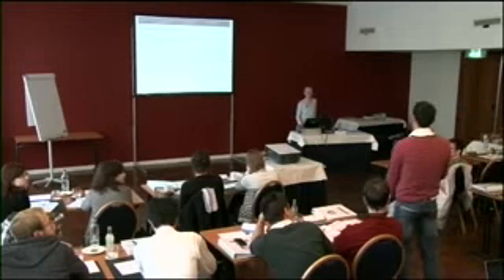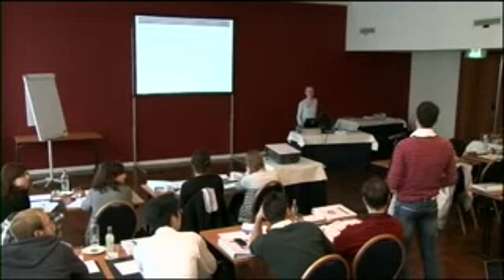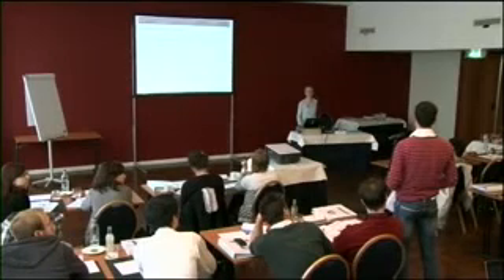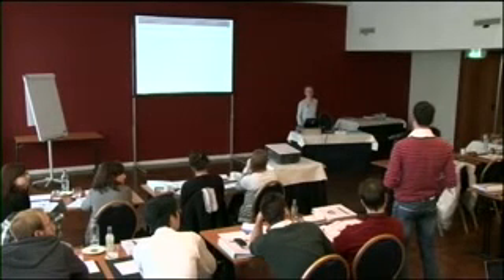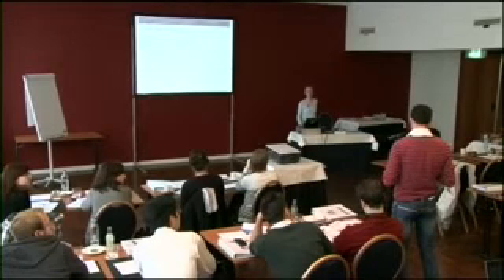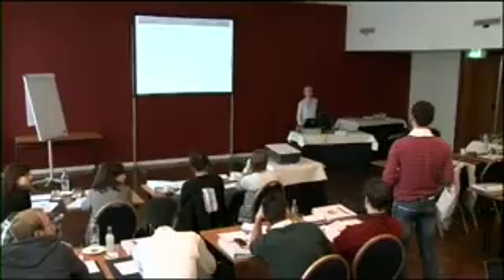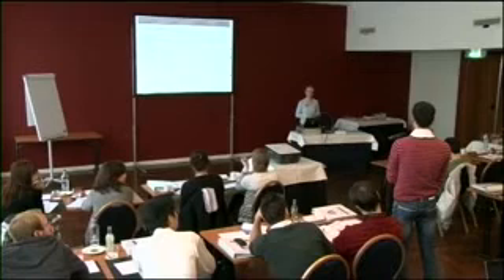In a slide, you said that we cannot determine the 3D pore size distribution from the 2D images. But isn't that contradictory to what Karen said yesterday, that the volume fraction of a phase is equal to the surface fraction? Yes, you need to assume that you have an isotropic structure, that it's similar in all directions. You need to assume that to be able to calculate the 3D pore size distribution. And do you usually do that? Is it acceptable as a hypothesis? It's done. As long as you state your assumptions, yes.